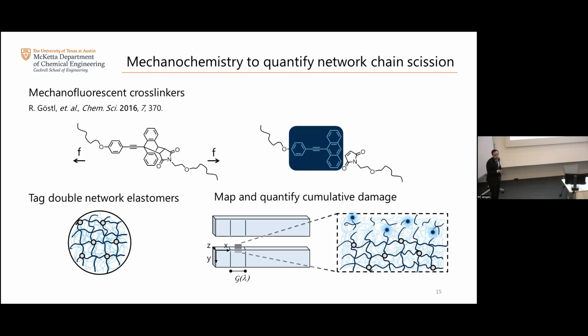And the technique, the reason why we can actually see the damage, because it's not very common that you can actually see the molecular damage, is because I have some training in polymer chemistry. And what I did is that basically I took these mechanophore molecules, which are these probes that were developed by Rint Sijbesma's group at TU Eindhoven. And what's very neat about these probes is that when they experience a molecular force that is on the order of the energy it requires to break a carbon-carbon bond, they undergo a retro-Diels-Alder reaction. And what's very neat about retro-Diels-Alder reactions is that they always give you some sort of conjugated group at the end that can be a fluorophore under a confocal microscope.